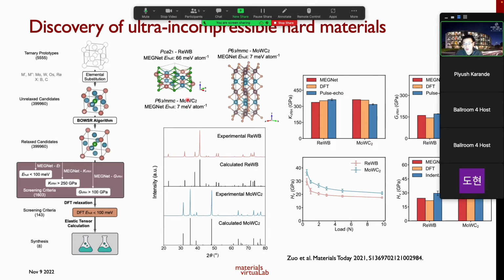Here are 2 examples of completely new crystal structures, one rhenium tungsten boride and one molybdenum tungsten carbide. And they actually have structures that are in very, very good agreement with the experimentally measured structures. So these are the XRD patterns. And also their measured bulk and shear modulus are in very good agreement with not just the DFT verifications, but also our machine learning model predictions. Okay, so this is one of the rare examples where we show that you can go from pure machine learning structure and property prediction to DFT structure and DFT property prediction, and finally to experimental synthesis and verification. So the entire pipeline is actually closed and verified.